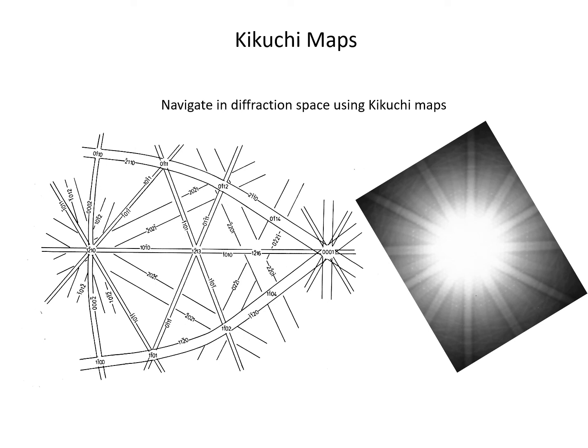These diffraction patterns in an electron microscope that you collect are real time. You can think of them as being attached to the crystal. So if we're looking directly through a crystal in the electron microscope along the C-axis, this is the diffraction pattern we would collect. And when we've got this diffraction pattern, we know we're at this orientation.